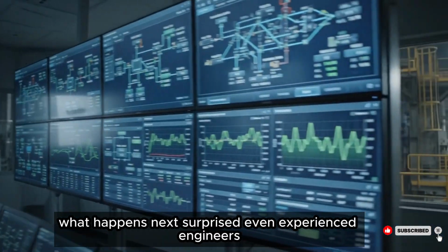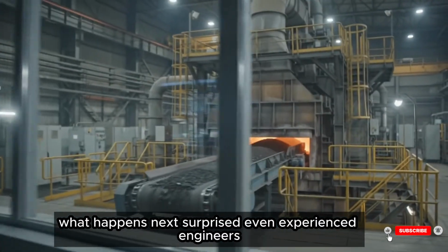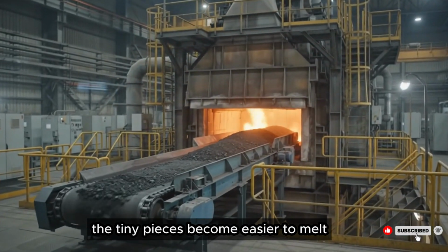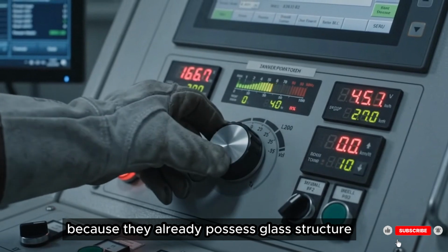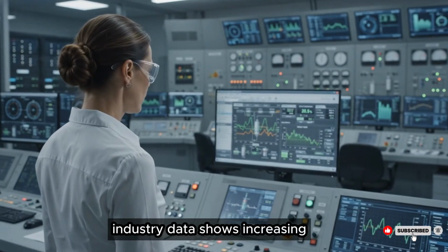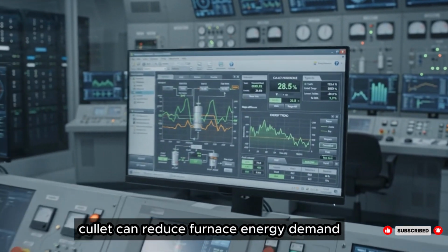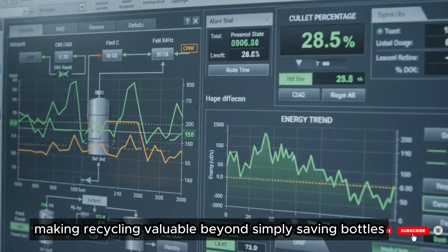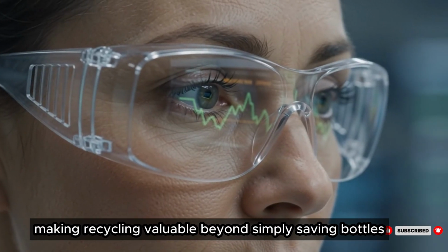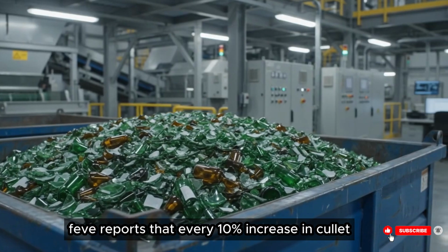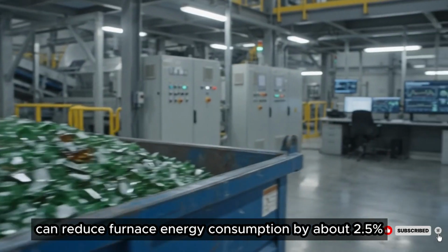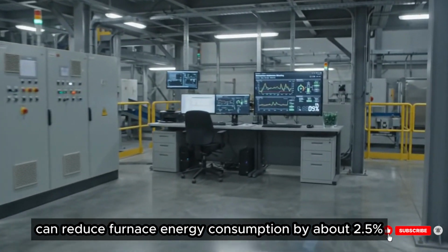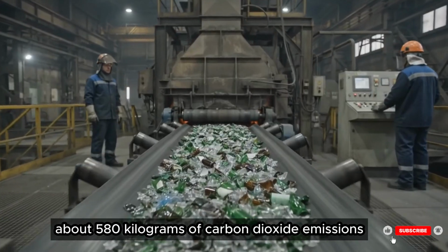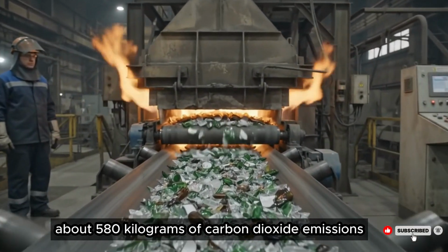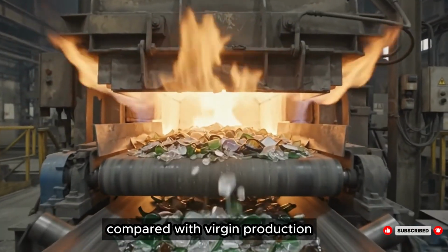What happens next surprised even experienced engineers. The tiny pieces become easier to melt because they already possess glass structure. Industry data shows increasing cullet can reduce furnace energy demand, making recycling valuable beyond simply saving bottles. FEVE reports that every 10% increase in cullet can reduce furnace energy consumption by about 2.5%, and 1 ton of recycled glass can avoid about 580 kilograms of carbon dioxide emissions compared with virgin production.